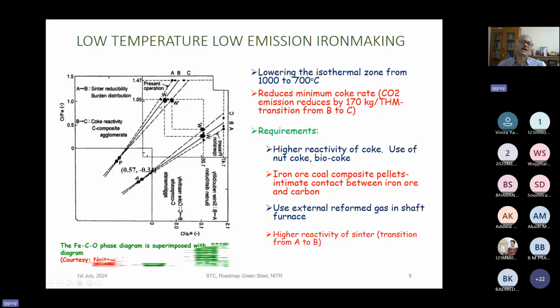And if you can reduce the isothermal zone temperature, you can find that this Wustite equilibrium point can be shifted to the right-hand side. As a result, the slope of the operating line will decrease, and that will reduce the carbon rate. So you can reduce the carbon rate further.